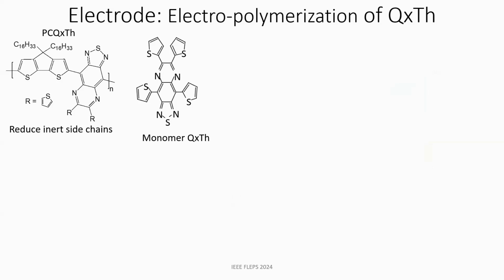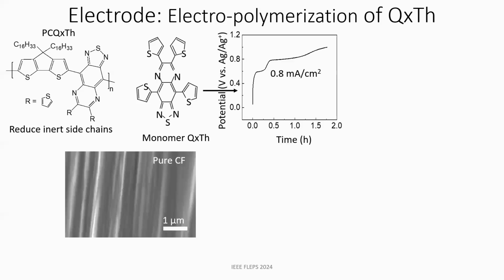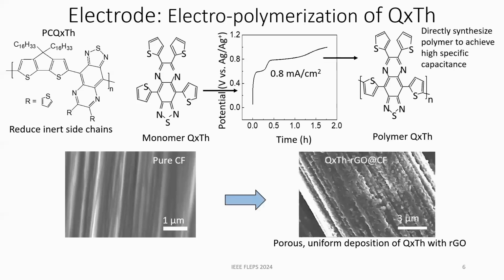Typically to deposit a polymer like this, we need solubilizing groups to make a solution and then coat the carbon fiber substrates. But once it's coated, these additional groups don't contribute anything to the redox capabilities. They just add extra weight and make thicker electrodes that reduce the power density, which is the key advantage of supercapacitors. So instead we came up with electropolymerization, where we drop-cast the monomer QXTH slurry directly onto the carbon fiber substrate. Then we apply a constant current to synthesize the polymer directly from the monomer, and once the voltage stabilizes, the reaction is complete.